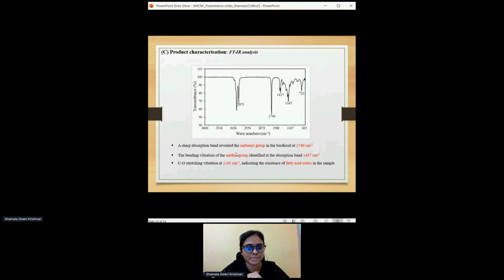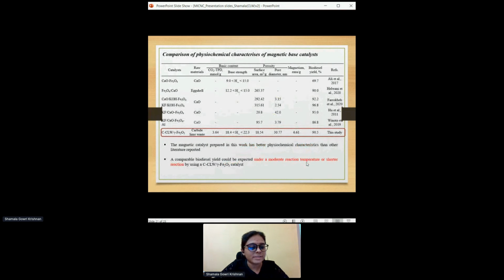Followed by the product characterization phase, where we found that the catalyzed sample has a carbonyl group, which is in the circle, and we found that the catalyst was able to catalyze the palm oil and produce a biodiesel. In the comparison of the physicochemical characteristics with other literature studies, we found that our catalyst has a better performance in terms of the physicochemical properties, and a comparable biodiesel yield, which we can accept at a moderate reaction temperature and shorter duration.